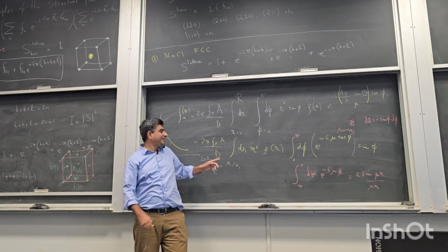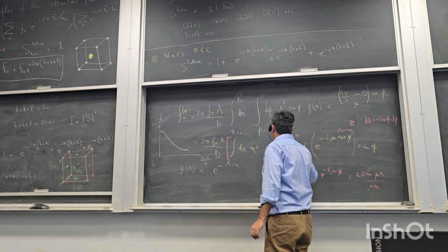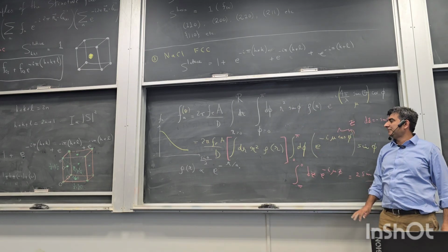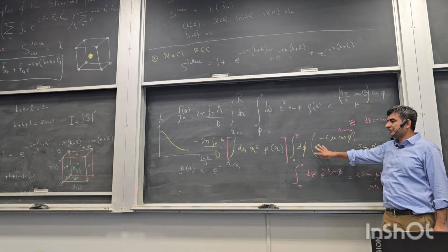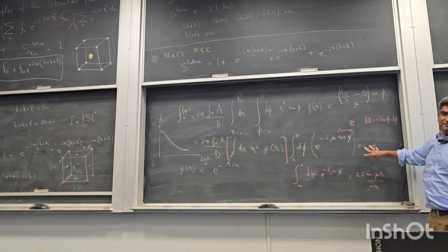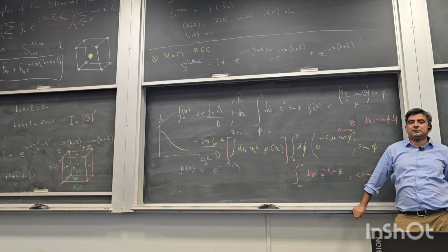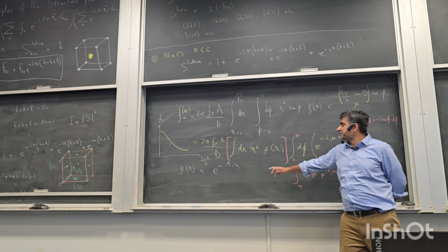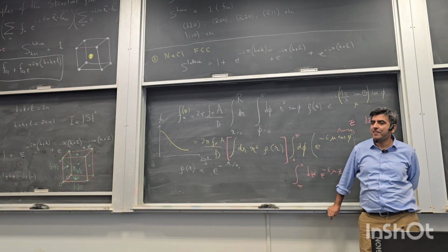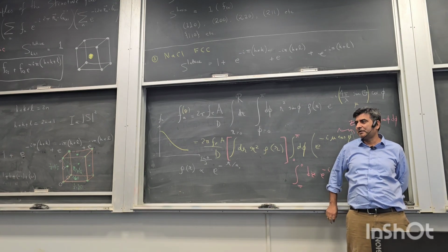Now what is this integral equal to? For theta equals 0 degrees, this entire exponential becomes 1. So what is this thing equal to? This is charge density. Total charge, which is called the atomic number.